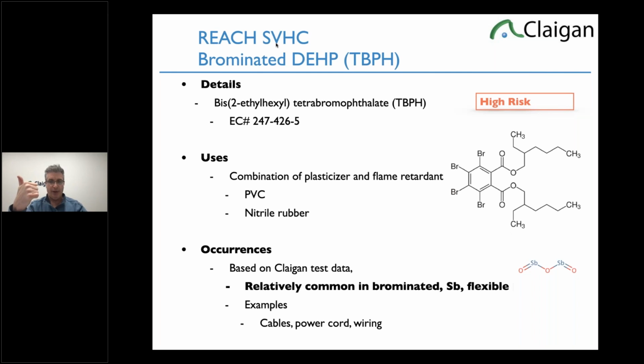Where we see this: PVC, chlorine, flexible, plasticized, brominated with antimony. Anytime we've seen flexible PVC with bromine and antimony, we've always seen this over 1,000 ppm. But again, you're looking at flexible flame retardant PVC, so cables, power cords, wiring. It is relatively common. It's usually with another orthophthalate, historically with DEHP, but more often now with DINP or one of the less regulated ones. We're looking at power cables and other wiring and cables that need flame retardancy and flexibility and are PVC. So this one is relatively common, but a very specific application. When we test for it, if you see chlorine, bromine, and antimony, we get tetrabromophthalate.